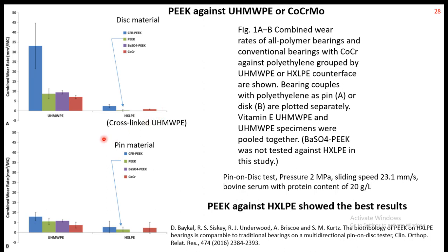Here people have shown that when PEEK is sliding against cross-linked UHMWPE, it gives far better results. The disc material is PEEK here, and cobalt chrome is this one when the disc material is cobalt chrome, and this result is for the wear of the disc part. As you can imagine, in a pin-on-disc machine test, both the pin and the disc wear out. So here we can see that wearing of the PEEK disc is much less compared to cobalt chrome molybdenum, and the pin part also, the PEEK pin was wearing less compared to cobalt chrome molybdenum.